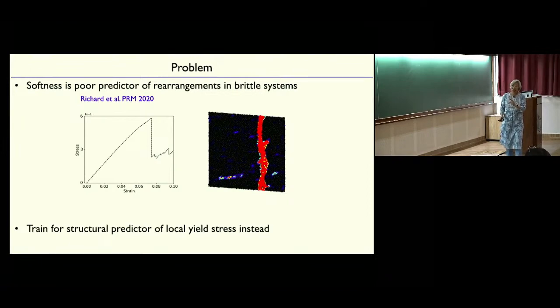Here, for this case, we actually train for a structural predictor of the local yield stress. You can take the neighborhood around the particle, shear it in different directions, and see the direction in which the yield stress is the lowest. These calculations were pioneered by Sylvain Patinet. And you can get out the magnitude of that local yield stress. There's a direction too, and this is why a tensor predictor would be much better, but we just do a scalar. As always, I'm not saying that we're doing the best thing, it's just adequate for what we're trying to do, and there are advantages to doing it better.